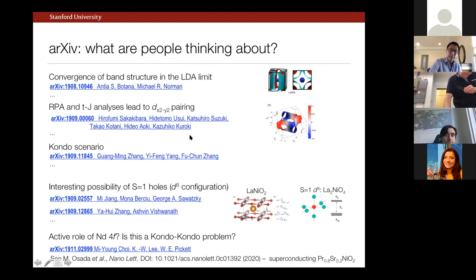The second statement would be kind of thinking about electronic superconducting instability, so random phase approximation or t-J models, kind of all lead to dominant dx² - y² pairing. That even though we have these small electron pockets here, essentially superconductivity is governed by something that in these theoretical approximations looks very cuprate-like.